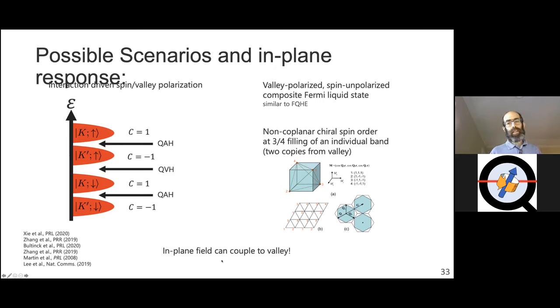So in looking at this, we'd like to see what's the effect of out of plane field, which should couple both to spin and orbital degrees of freedom, and in plane field, in the plane of the sample, which should couple primarily to spin, although that's an oversimplification, it can also couple to the valley.